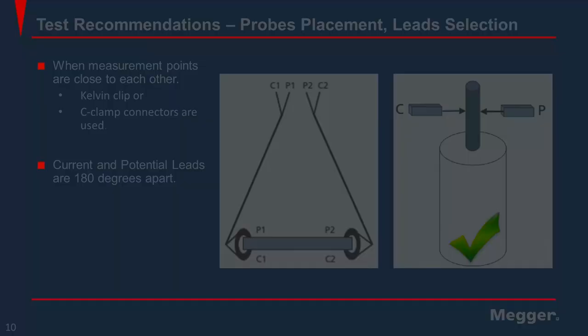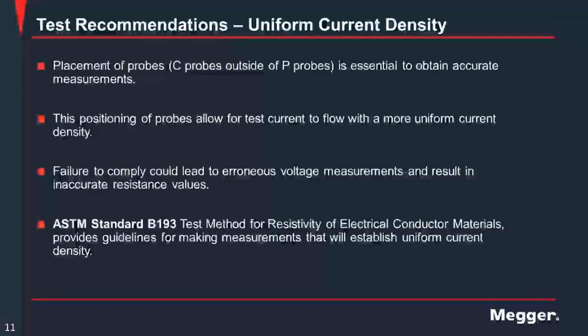Okay, so now we understand, or at least understand deeper, how to place the probe. The position of the probe is really crucial to get accurate low resistance. Remember, the current probe should be outside of the potential probe. You need to follow this recommendation. This position also allows the test current to flow with more uniform current density. In case this method is not followed, it can cause resistance measurement failure. Sometimes the resistance of the probe or any other resistance may be included in the measurement, and then you will not get the accurate measurement anymore.